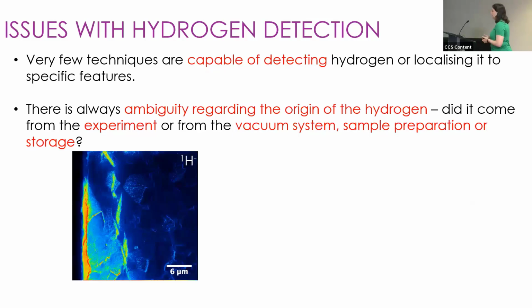Here's an example of a zirconium alloy that we're looking at in cross-section. This is the hydrogen image from the NanoSIMS. Over here, this dark region on this side is resin that we use to mount the sample. Here we have a thin oxide layer on this zirconium alloy, and here we have the bulk metal. Now, zirconium alloys very often have hydrides contained within them, and we can clearly see a layer of hydrides along here in this hydrogen image. That's as expected. But what wasn't expected is this smudgy region we get down here in the hydrogen map, which looks like it contains a lot of hydrogen. So is that real from the experiment, or is this an artifact of storage, sample preparation, the vacuum system?